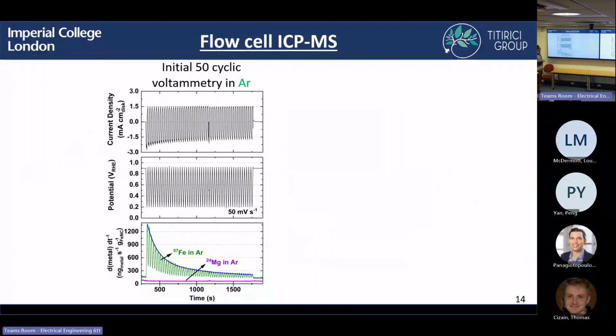So first, looking at the initial 50 CVs in argon, we can see here, on the bottom, measuring from the ICP-MS, how the concentration of our metal is being measured over time. And then in the middle figure is just our potential as we go from 0.9 to 0.2 at 50 millivolts per second. And then the current density, this is in argon, so we have a relatively low current density, and this is just coming from capacitance.